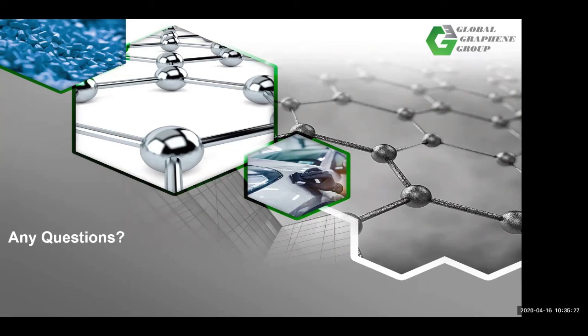If they want to go higher in thickness or have more heat flux, they stack them in different layers. For example, from 20 microns to 70 microns, they will stack 3 layers of 20 micron products and put 5 micron adhesive tape in between, so they can dissipate more heat. But the issue is, the 5 micron adhesive tape offers heat resistance, so the heat dissipation path is less smooth, and it's not as effective. But for our AT1500, we don't have these issues.